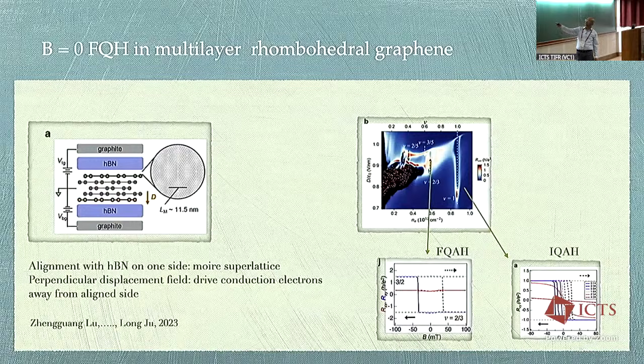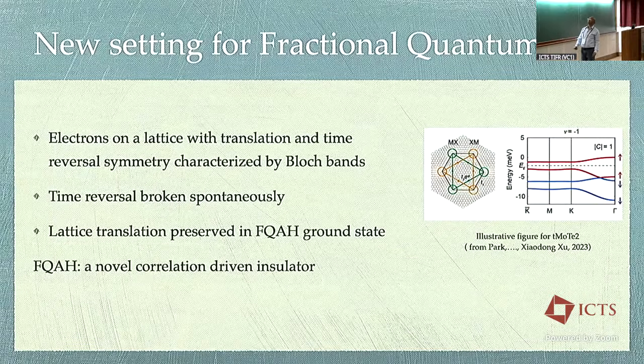So this is at mu equals 1, integer 1 electron per Moiré unit cell. And you see, again, hysteresis, and then beyond the coercive field, quantization at h/e squared. And at 2/3, you see hysteresis and quantization at 3/2 h/e squared. Right? So this phenomenon of quantum Hall in zero field on a lattice system definitely exists. It exists in experiments, not just in the world of theory. So there's a new setting for the fractional quantum Hall effect.